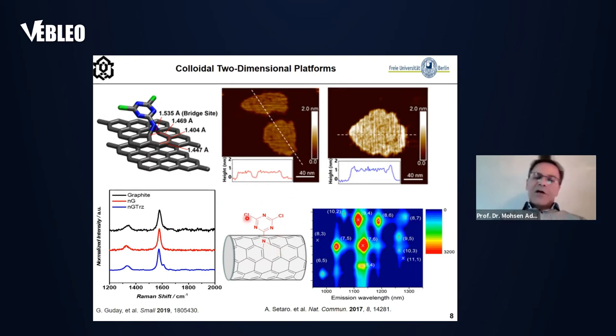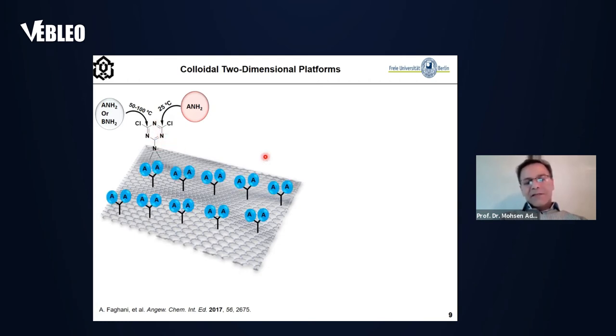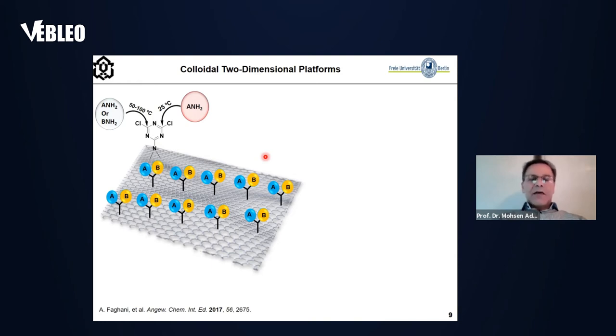This feature of covalent functionalization is beyond today's talk. I want to discuss another feature: from the chemistry of triazine, we know we can substitute the first and second chlorines of the triazine functional group step by step at different temperatures. By this method, we are able to control the density and type of functionality on the surface of the graphene sheet. Now we have a good method to manipulate the surface structure of our platform in a controlled manner and produce different platforms for different two-dimensional polymerizations.